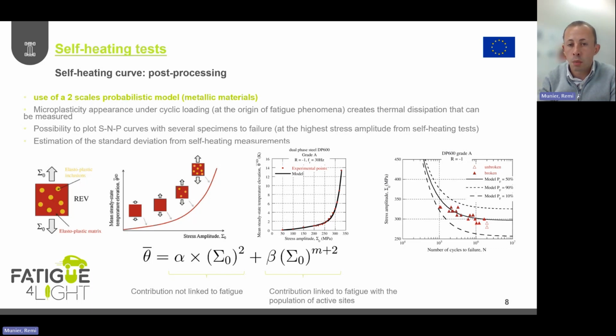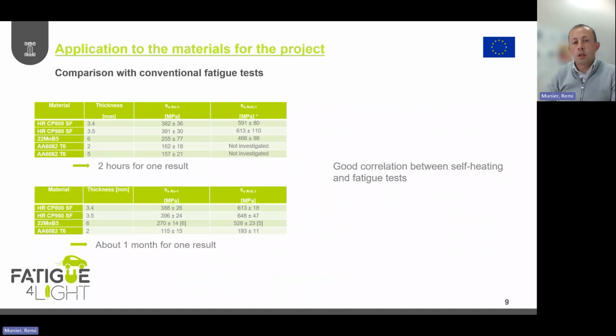And here on the graph, we can see the comparison between experimental curves obtained in fatigue and then in black, those obtained with self-heating measurements. So for the comparison between the metallic materials, if I can say so, for the project, we can observe for both loading ratios, at the top, self-heating measurement results, which are obtained with one specimen in several hours only, and then on the bottom, conventional fatigue test results, and we can see a good correlation between self-heating and fatigue tests, which are obtained in a very reduced time, which is what we wanted to obtain.